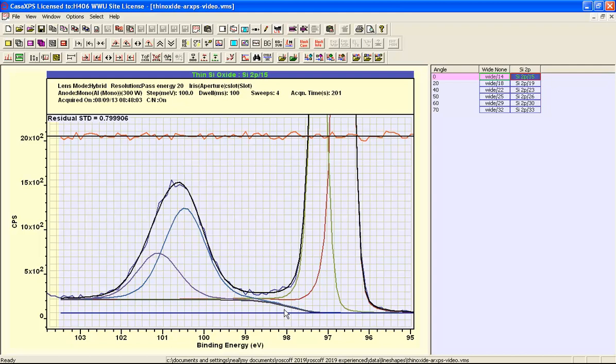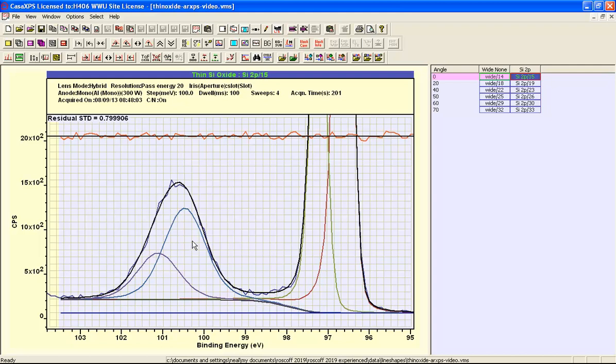So this offset of this background that is calculated from these elemental peaks is offset to model a semiconductor behavior. And beneath the oxide peak, these represent a flat background which is consistent with a thick oxide film looking at the same oxide peak.